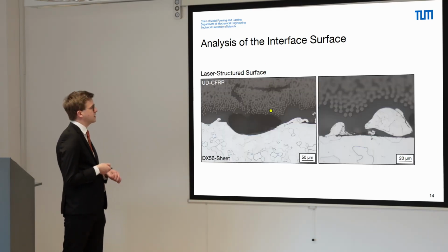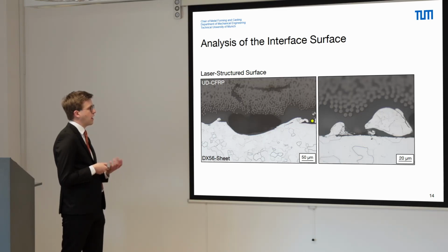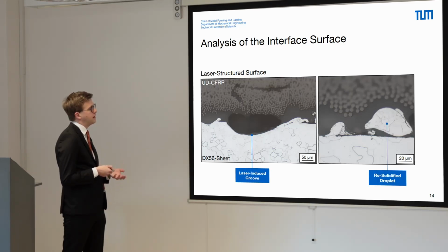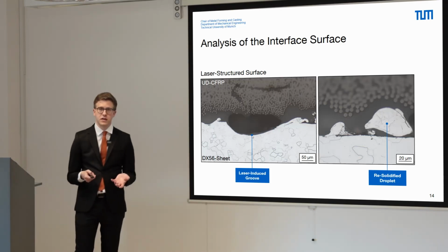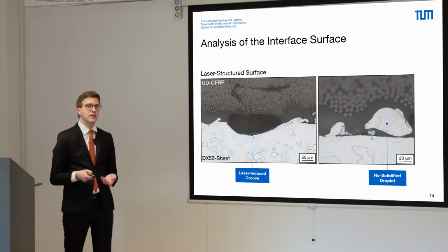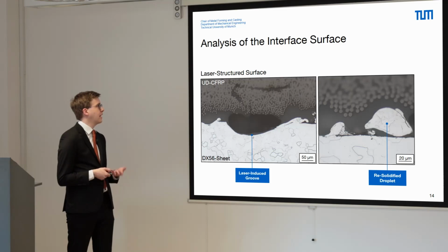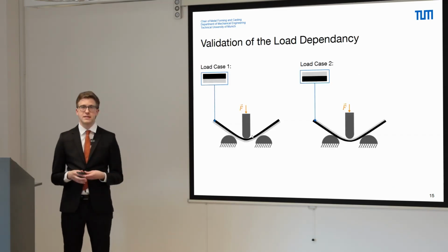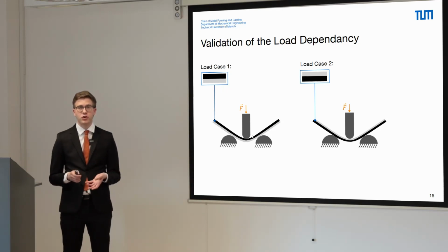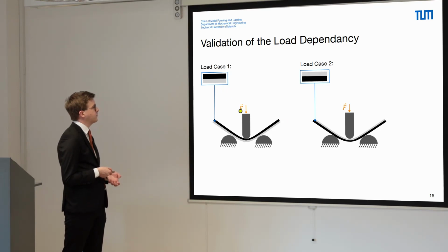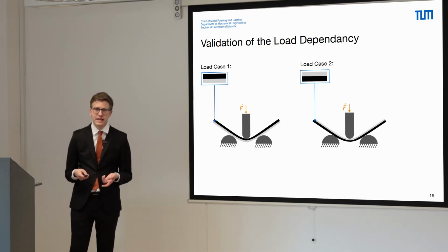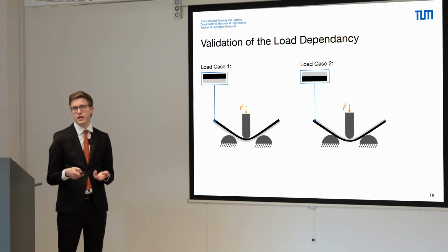For the laser surface structure, we can again see the more rounded structure. We can see the results of the melting and the resolidifying of the laser rays on the sheet surface, and here a laser-induced groove. To conclude, also the laser structuring surface strategy was able to generate sufficient bond strength, and now we can see the validation process. Therefore, we started with a preliminary study in which we laminated the sheet metal component with the UD fibers and performed two different experimental configurations of the three-point bending test.